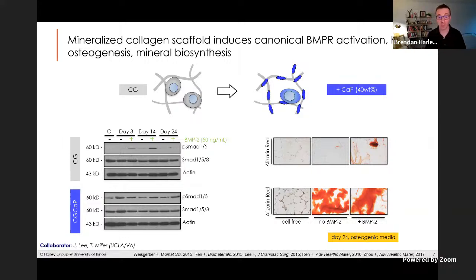The traditional way one does it is you add a lot of growth factor, particularly something known as BMP2. It's a cytokine that will drive differentiation of these stem cells into bone. It is used clinically, but some of the challenges are it's incredibly expensive and it's very hard to keep this small molecule just in your material. And so you end up using a lot of growth factor and it can diffuse outside of the wound site and form little bone nodules away from where it's supposed to.